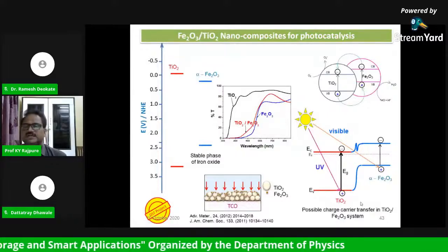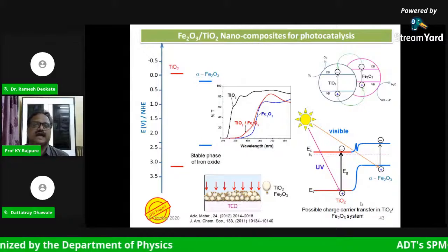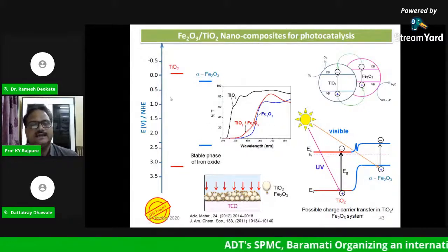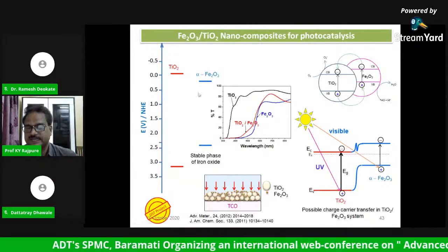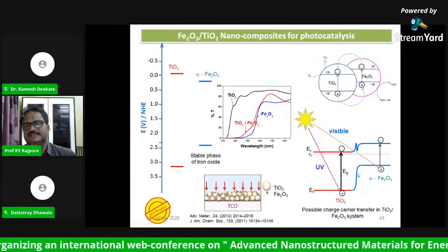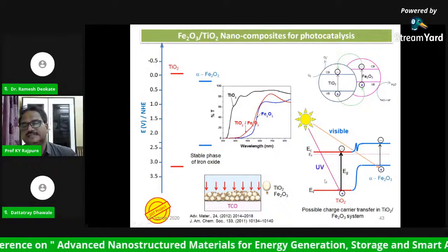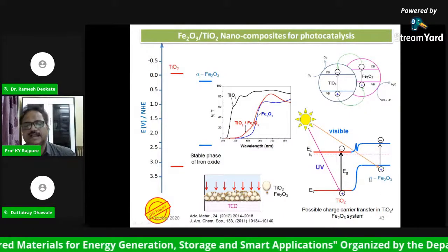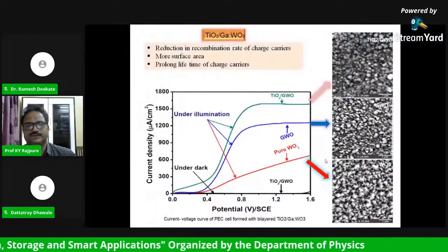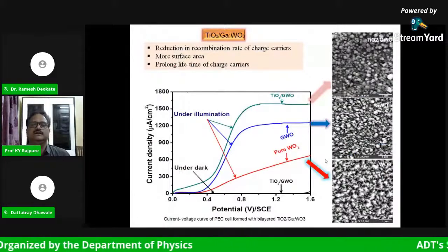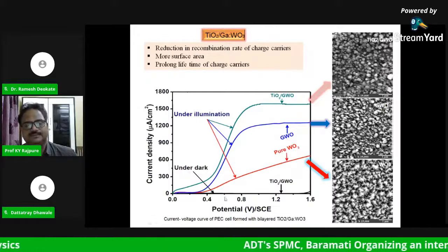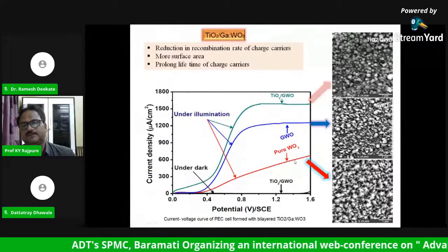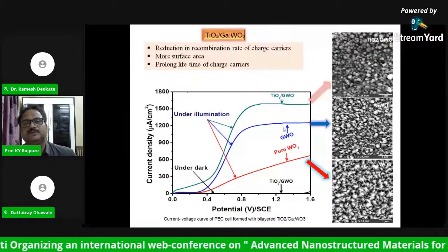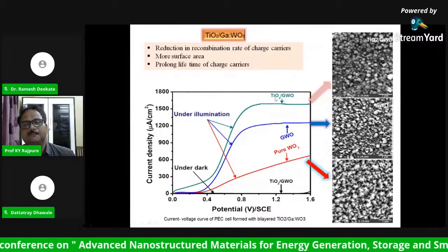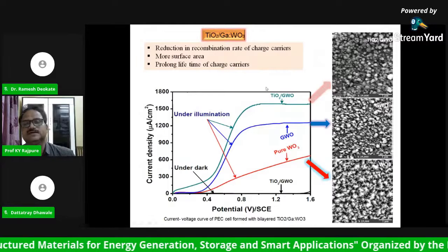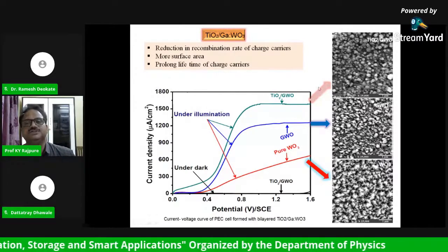In one of our major projects, we made the composite of iron oxide with TiO2, where the band positions of iron oxide and TiO2 are shown. This is the first type of heterojunction, and the band bending gives you the depletion potential, and UV is harnessed in TiO2 and visible is harnessed in iron oxide, thereby increasing the photocatalytic efficiency. We have made the composite of TiO2 and gallium doped tungsten trioxide also. So this is the IV diagram in the photocatalytic experiment. For pure WO3, the current is less. For gallium doped tungsten trioxide, the current increases, and for the composite between TiO2 and gallium doped tungsten trioxide it increases still further. So here you can see the contribution of making composites between various semiconductors.